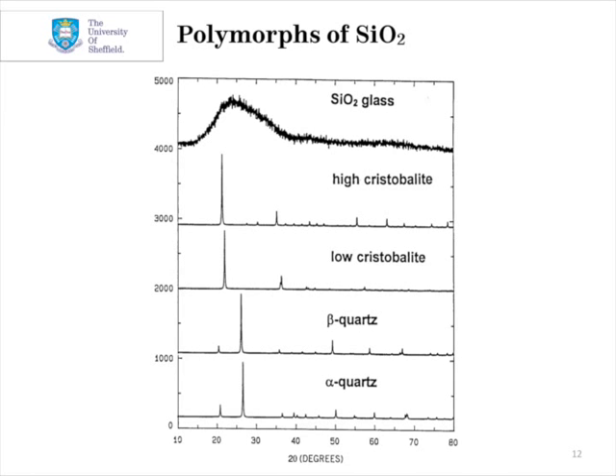Low-cristobalite and high-cristobalite have different crystal structures and you can see the diffraction patterns for these look quite different. At the top we have the diffraction pattern from some silica glass and we can see simply here a broad amorphous hump centered around about 25 degrees 2θ and no strong, narrow, bright reflections indicating that this material is in fact a glass amorphous material and there is no long range order.